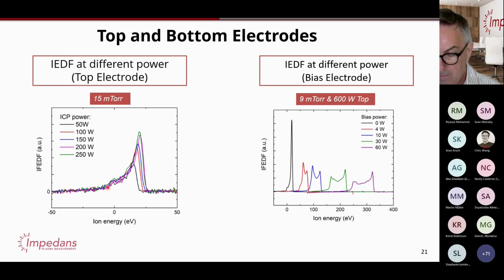You can also scan around 0. Now there's a few questions on how to interpret that data, but you can scan around 0. There is generally a distribution of ions that you could see around there. But the one thing I'd say is from simulations of RFEAs, the electric fields inside them can be a little bit bent, or a little bit complicated, not exactly uniform. So in reality, your resolution depends on the quality of how you've built the sensor. If you just throw a sensor together, your resolution is going to be no better than 1 eV, even if you use 0.1 steps. In terms of an absolute value, I wouldn't trust it, but in trends I would. But 0.1 is not unachievable, let's say.